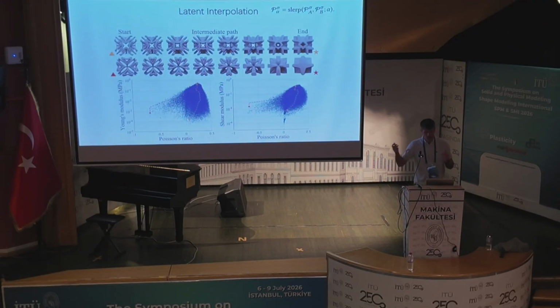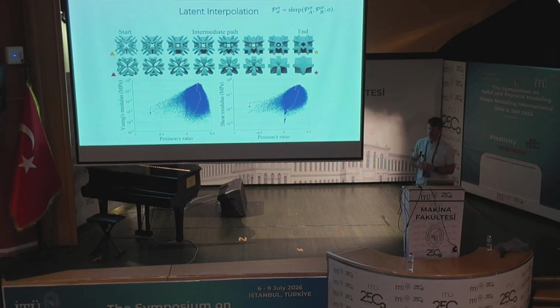And to see how well this works, we can now actually look at interpolation in this latent space. So here you can see two start models, which are truss structures with low Young's moduli and small volume fractions. And at the end, you see models that are plate structures, which have high Young's moduli and large volume fractions. And then we just interpolated in latent space. And you can see here, I would say the interpolation works quite nicely.